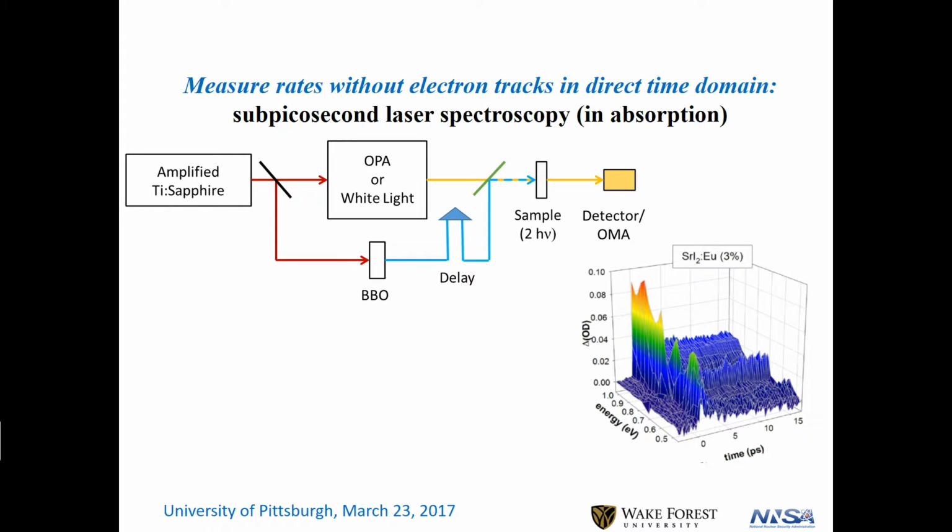But anyway, okay, so that was the so-called Z-scan part. I realize there's only like 5, maybe 10 minutes left. So we'll switch to another use of lasers, and that's just straightforward pump probe absorption spectroscopy. It's a standard technique. We need to cover from infrared as far as we can go to ultraviolet as far as we can go. So we use an OPA for the infrared through visible, and then we use supercontinuum for visible through ultraviolet.